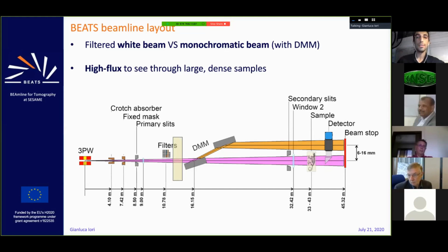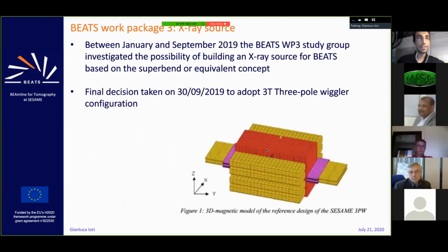And the important thing in this case is to have a high flux to see through large, dense samples. And this is why my colleague Axel already showed you that work package 3 was actually responsible for designing and taking a decision regarding the X-ray source for BEATS. This was taken in September last year, and work package 3 decided to adopt a 3 Tesla 3-pole wiggler design. So it is essentially one big pole surrounded by 2 auxiliary poles. In this way, the source can be installed in a straight section of the accelerator.